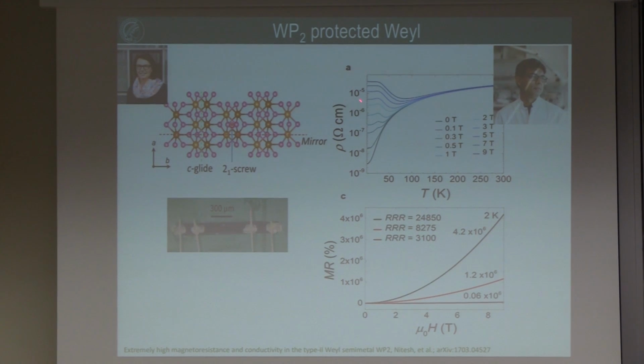If you do the transport measurement, it looks again very typical for all these Weyl semi-metals, Dirac semi-metals, and so on. We have a giant magnetoresistance effect at low temperature. At a certain temperature, we have no magnetoresistance effect. This is very typical for this material. They have no magnetoresistance, and then they suddenly split. So if you apply magnetic field, you get a behavior like a semiconductor, and then this plateau.